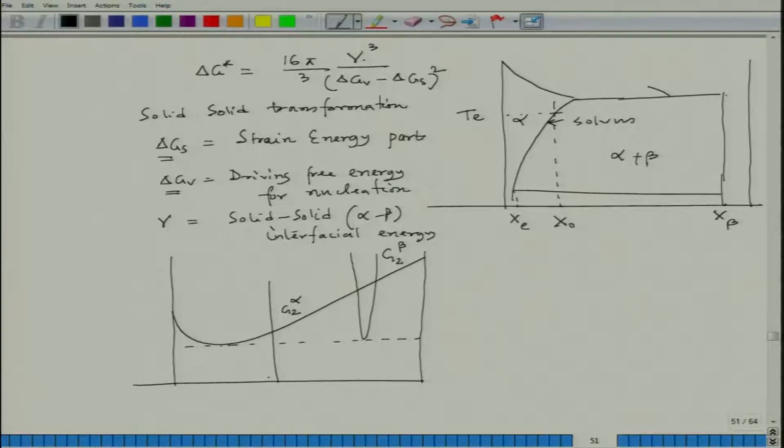Now the equilibrium composition at that particular temperature. This was my x0, that initial composition, this is xe and this is x beta, which corroborates with these compositions as per the phase diagram. Now at this point, if I draw a tangent, in order to form this particular composition, my free energy gradient would be this much, which is nothing but delta Gv as per our previous concept. This is basically the molar quantity, that is free energy in joule per mole.